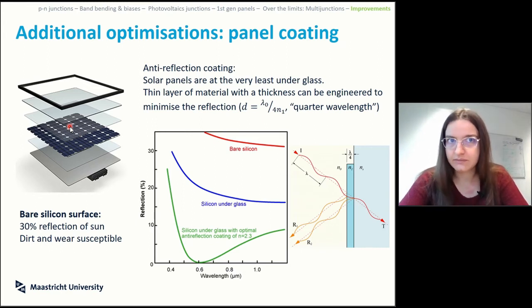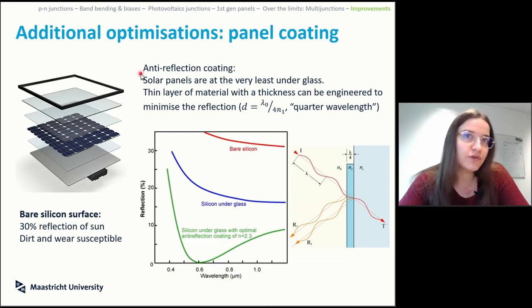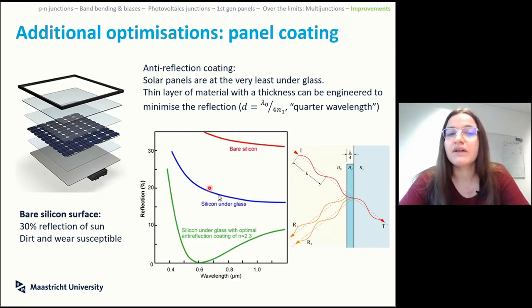You actually want to cover them in a very specific way, because you could just put a layer of glass of an arbitrary thickness, and this will already improve how nicely your silicon is able to operate, because you tweak the reflection already. But since reflection is a very physical trick, you can tweak the thickness of your glass to make sure that at the right wavelength in which you want your material to operate, you are not reflecting the sunlight off. The bare silicon has 30% reflectance, which already takes off a very significant amount of the light that you want to use.